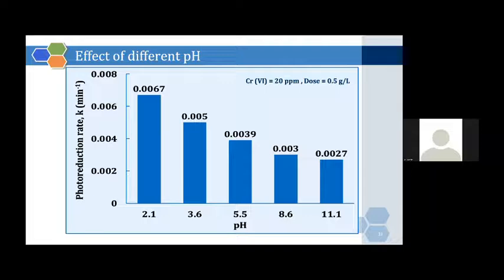At higher pH value, the surface has become more negative, which resists the adsorption of negative chromate ions. Additionally, at higher pH, the deposition of chromium hydroxide on the photocatalyst surface reduces the contact area of the catalyst with the reactant, which decreases the photocatalytic efficiency. This serves as a barrier to photocatalytic electrons for chromate ions, which led to a photocatalytic decline.